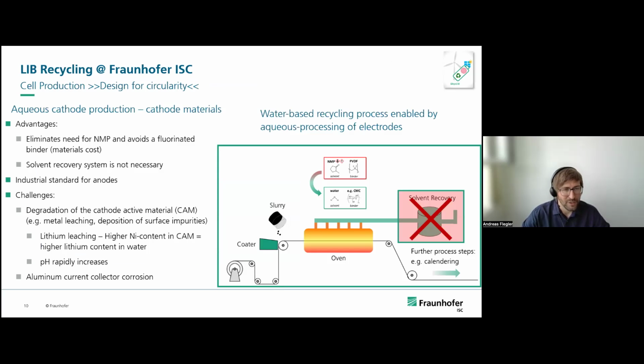This also brings a lot of challenges with it. We have a degradation of the cathode active materials with a high nickel content. So we have a leaching of lithium, an exchange of lithium and protons, and also the pH value increases, and we get an aluminum corrosion of the current collector. To prevent it,